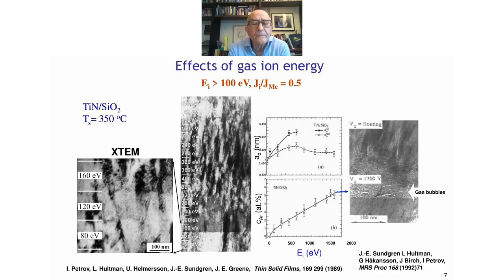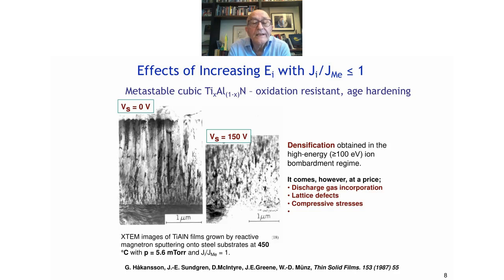So if you go to the next slide, I introduce to you titanium aluminum nitride, which has been used for now 30 years as an improvement on titanium nitride as an oxidation resistant coating and for hardening, which I'll also talk about. As soon as it grows into the cubic phase, to the left, it is identical to the zone 1 structure that I showed you. It behaves just like titanium nitride. If we apply bias at 150, we get this renucleation. So densification, again, comes at the expense of discharge gas incorporation, lattice defects, and compressive stresses. Next slide.